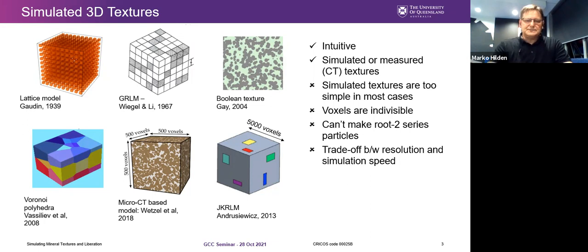So on this large one here, 5,000 voxels on a side, that works out to, if each voxel is 1 byte of memory, 125 gigabytes. And that's clearly a very large memory structure to process, even on very good computers. So the simulation speed is actually very slow. You can simulate a smaller model, but it then has less resolution, so you have this trade-off between these modeling approaches.